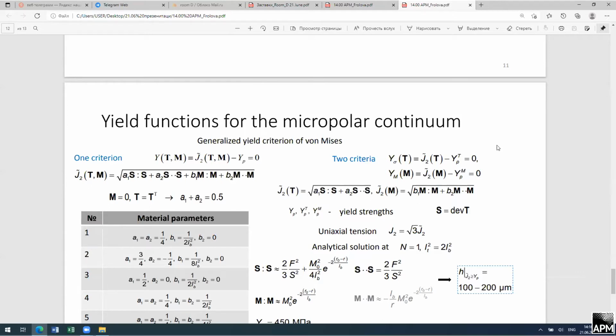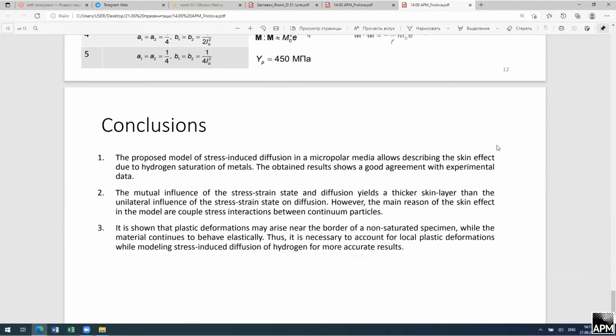And the main question here is about the material constants that are present in the intensity expression. And here we use different values from different papers. However, it was found that all of them lead to more or less the same result, and we obtained that the area where the yield function becomes negative is about 100 to 200 micrometers. And therefore, yes, it's really necessary to account for possible plastic deformations in the vicinity of the border. And here you can see the conclusions.